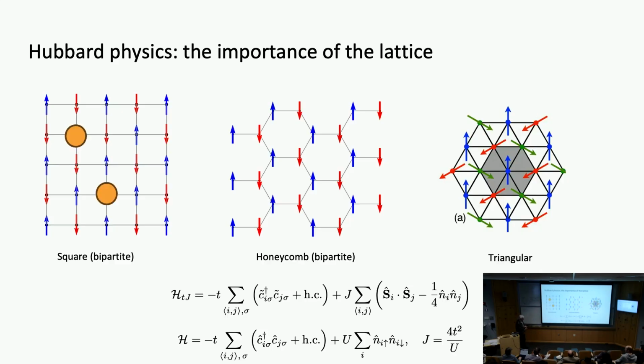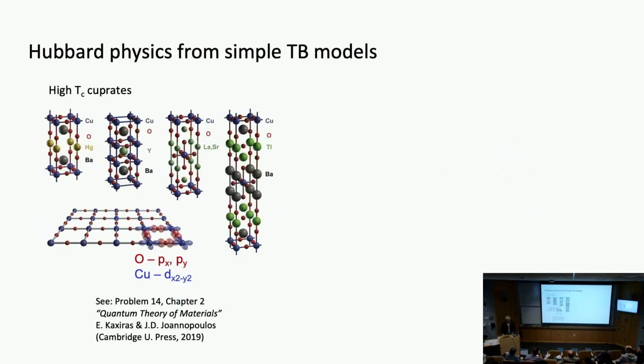For example, if you have two holes in this antiferromagnetic system that are far apart, you break so many antiferromagnetic bonds around this one and so many around this one, 4 here and 4 here. If you bring the holes closer together, you only break a total of 7 antiferromagnetic bonds. So that's an energetic incentive for the holes to bind. And it's believed that that kind of mechanism is related to the superconductivity seen in high temperature superconductors.